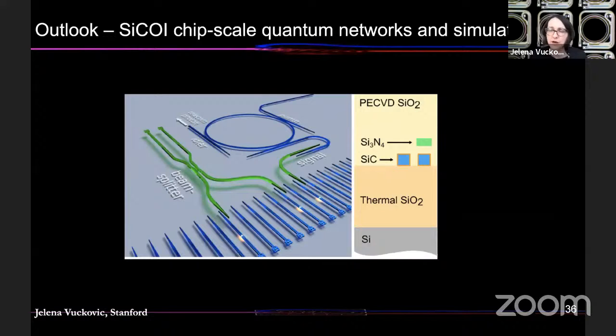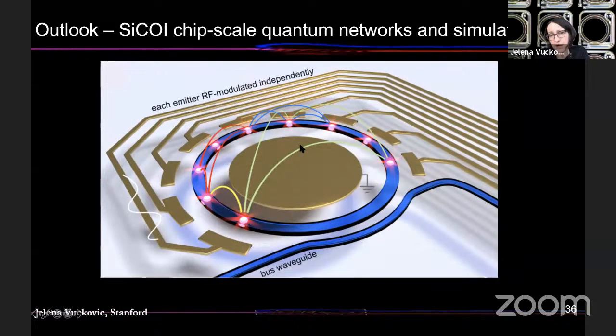In any platform that you work with, there are always imperfections and there is always imperfect yield, which means that you need some level of reconfigurability. This is what you do with optical tweezers for atoms, or in superconducting qubits, you also need to rewire, reconfigure the circuit to bypass non-functional qubits, right? We need to do the same. And in silicon carbide, that will be relatively simple because you can add another layer of lithography to connect the good working qubits that you identify in your system. And that could be done, for example, in a layer of silicon nitride. And then you don't really need any other materials for your quantum frequency conversion or interfacing for fiber to fiber optic network. And of course, on top of this reconfigurability, you also have the electrical reconfigurability that I was talking about previously, where you can apply an electrical signal, either optimized periodic driving or just DC Stark shift, in order to reconfigure your network.